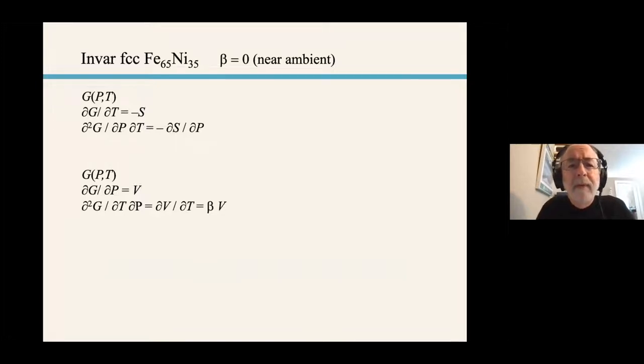we looked at the behavior of the thermal expansion, and as you just saw, the reason for doing that relates to the free energy, the Gibbs free energy, whose natural variables are pressure and temperature. Let's take some derivatives here. The first derivative is just the entropy, okay, with respect to temperature. We could take the volume derivative, or the pressure derivative first, we get the volume. Then we take the next derivative, with the other variable, in this case with pressure, and we get how the entropy varies with pressure. Now here we take how the volume depends on temperature, which is the thermal expansion.